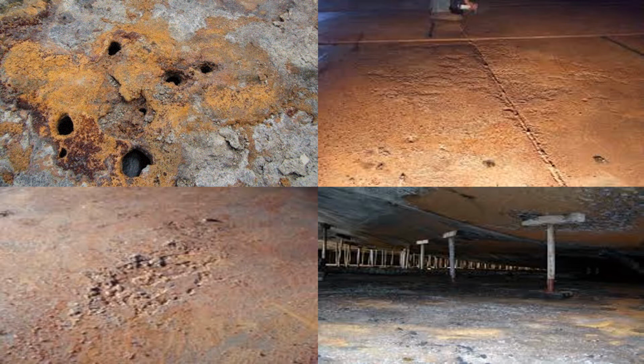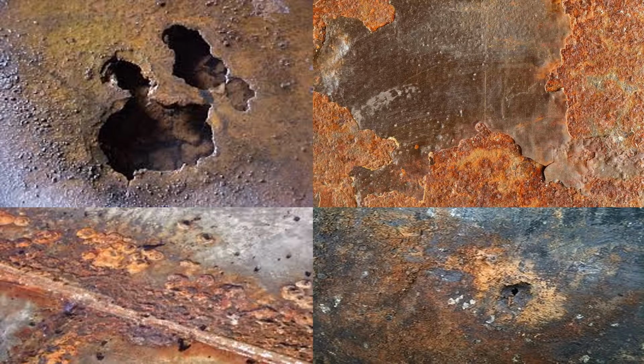The bottoms of above-ground storage tanks are susceptible to corrosion, especially if the tanks are close to salt water or subject to stray electrical currents in the soil. If an above-ground tank bottom is corroding, it must either be replaced or coated with a thick film, fiberglass reinforced lining with a 60 to 65 mil dry film thickness.